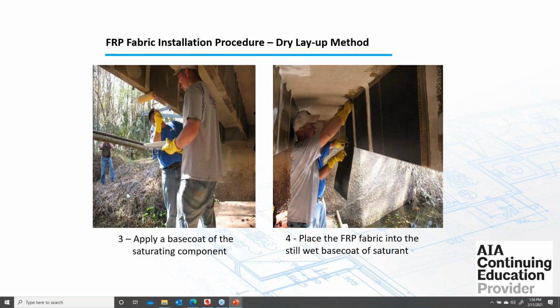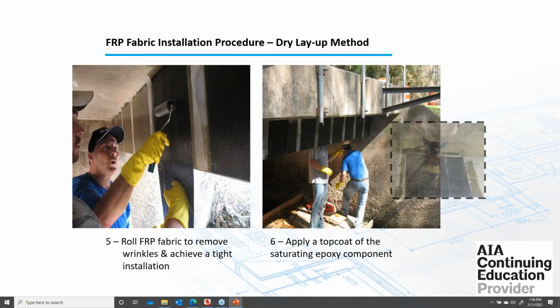The third step is to apply the first coat of the saturating component, then place the FRP fabric into the still wet base coat of saturant. After that, you can roll the FRP fabric to remove wrinkles and achieve a tight installation, and finally apply a second and final top coat of the saturating epoxy component.